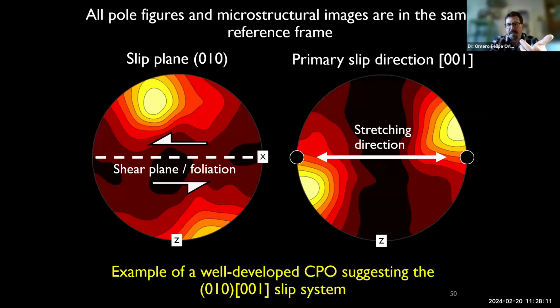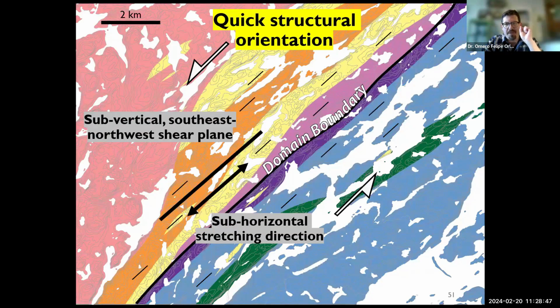So tying that back into the overall theory of how dislocations move on slip systems, you need a plane for them to be moving on, and then you need a direction for them to be going in. And so when you relate this back to the overall shear zone kinematics, you find that you have particular slip planes and slip directions that are really well aligned generally with the overall sense of plastic movement in the shear zone. And so that's probably the slip system that this particular mineral was using in order to accomplish this ductile deformation. So that's why EBSD is a really, really useful tool, but it's also really good at measuring grain size, which we're going to get to in a second.